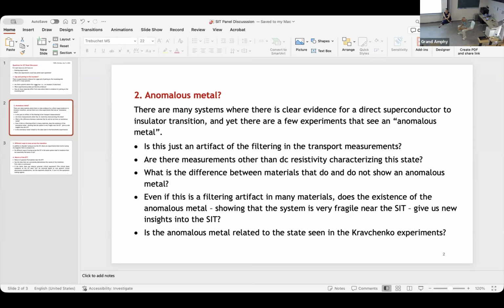Within this random resistor network model, you can actually have this drop. The fading of the superconducting transition is just given by the fact that you don't have a percolating path throughout the sample. If we do that at very low temperature, we expect everything to be coherent, and also the metal, the proximity effect between the grains, and so on.